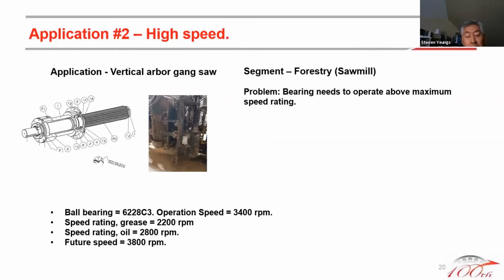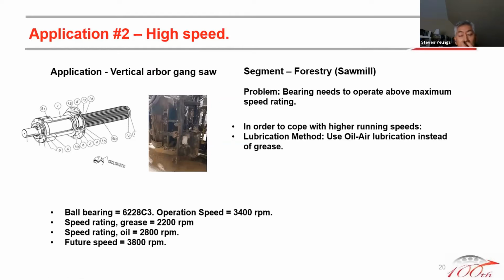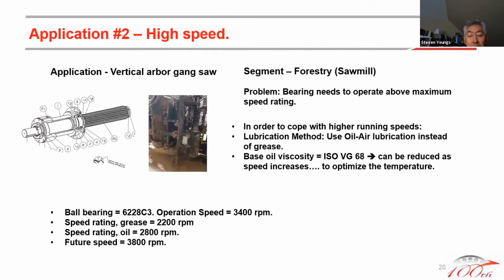The future speed, as we know, is not only 3,400, they're pushing towards 4,000 RPM. So what can we do about this? In order to cope with the higher running speeds, in this particular case, we eliminate grease. We're using oil-air lubrication. The selection originally was 68, but as speed increases, generating the oil film is not a problem. Generating too thick an oil film could be a concern. So that can go to a 46 weight or 32 in the future. And a bearing with a higher precision grade, we can push for another 10% increase in speed capability, can also be considered. So for some high speed applications,